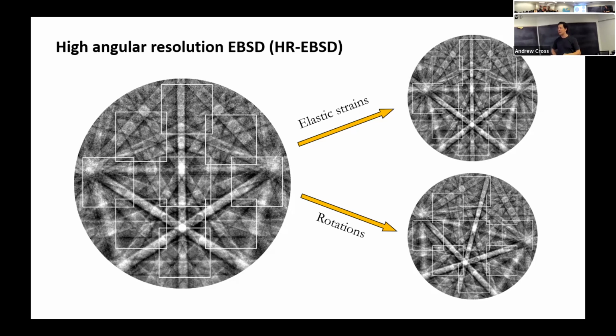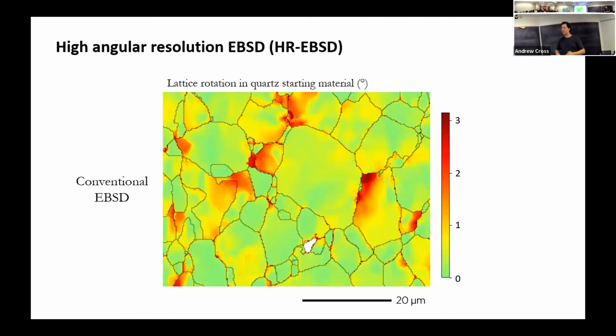These can then be used to resolve even smaller defect densities. The two bits of information that we're interested in here, and that we can pull out, are, first, the elastic strain, which is just the squeezing and squishing of the pattern itself. If we know the elastic constants of our material, we can get elastic stresses and residual stresses from this information. And we also get rotations, which we can then use to build up a distortion tensor for our grains, and from there get out dislocation types and dislocation densities.